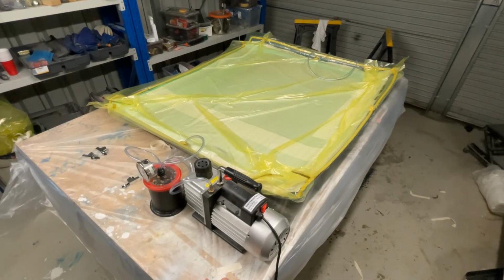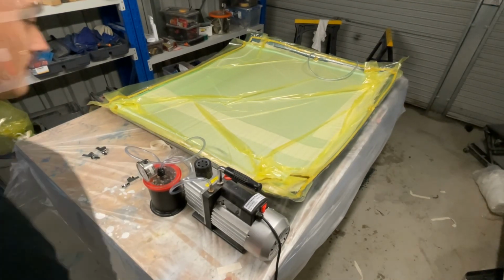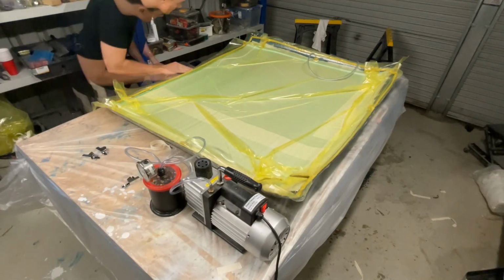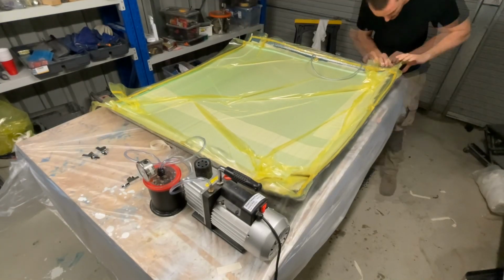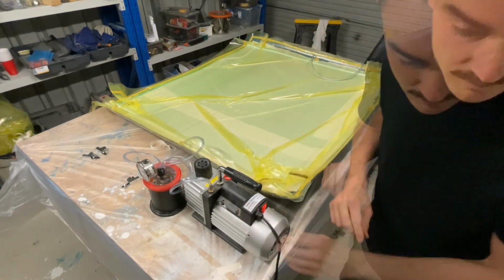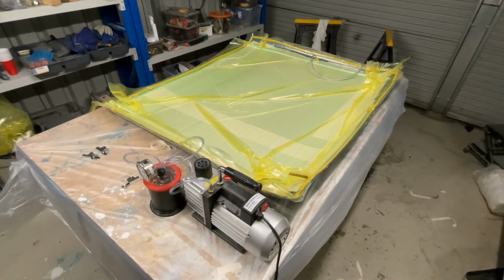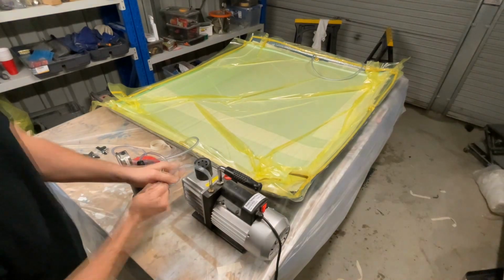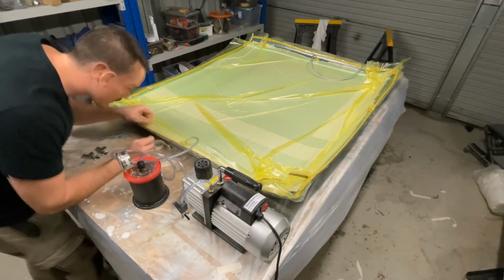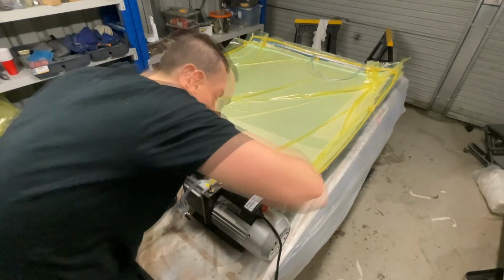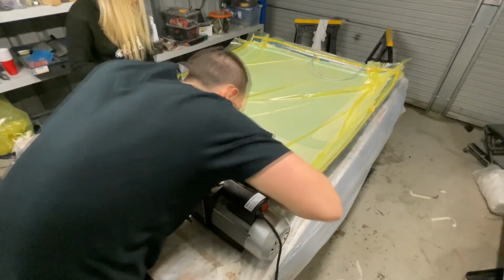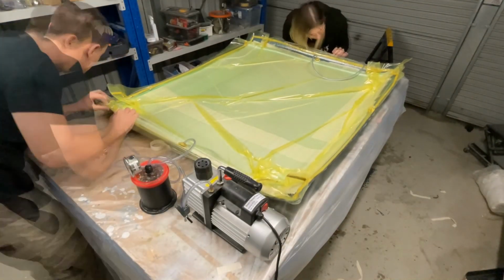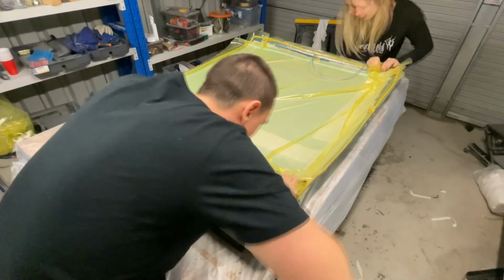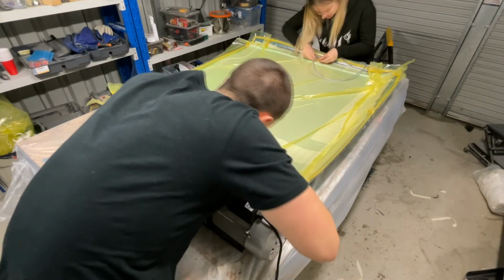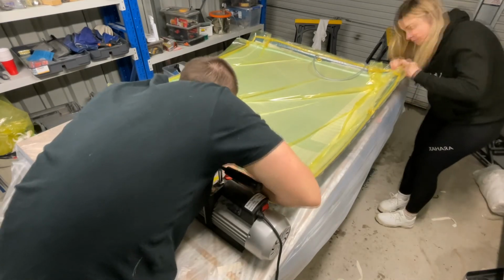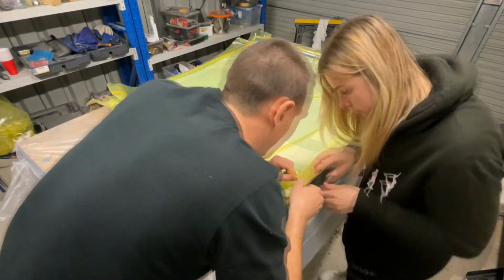And now it's time to perform the vacuum drop test on the mould. Straight away after drawing the vacuum, I could hear the hissing of air being drawn in through multiple places. So I had to go around really pinching the vacuum bag onto the tape to really ensure that any of those hisses had stopped. And even after you do stop the leaks, which you can hear, there's likely to be quite a few more which you don't hear. So you've really just got to go around really mushing the vacuum bag against the vacuum tape and against the mould, especially in areas where there's any folds or creases in the bag.